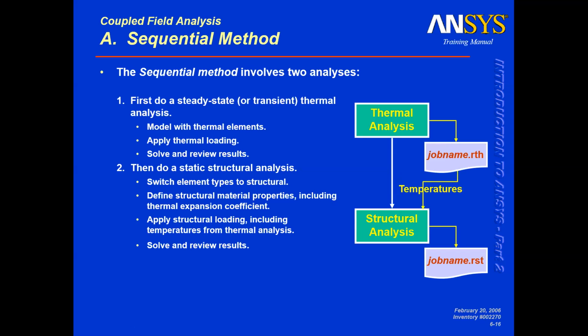Electrical, transient, then steady state situation, leading to a lot of thermal strains. And then the thermal strains giving rise to what are called structural stresses and strains. And then we had to find out what was the influence of these Joule heating, or say the thermal component due to electrical heating, and the hygrothermal component on structural aspects of reliability, which would not lead to, say, delamination or any undesirable failures. Even if one wire bonding, gold wire bonding goes bad, it's gone.